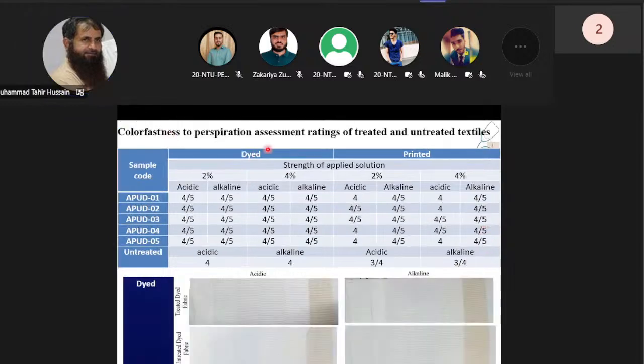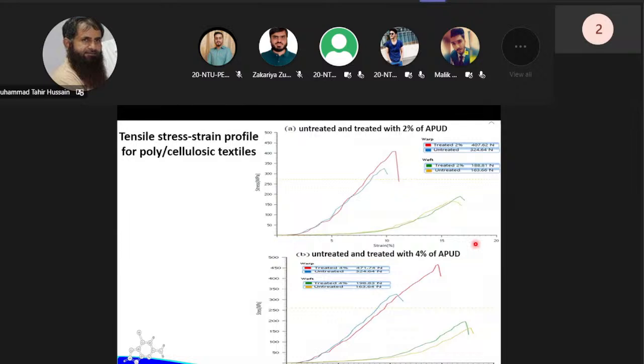Similarly, the color fastness to perspiration was observed, and that showed a similar result. But we found that there is not much big difference between the lower concentration and the higher concentration of the materials. And also we determined the tensile stress strain of the materials, and this is the graph of 2% APUD. Here the red line is showing the treated fabric, and the bluish line is showing the untreated fabric.